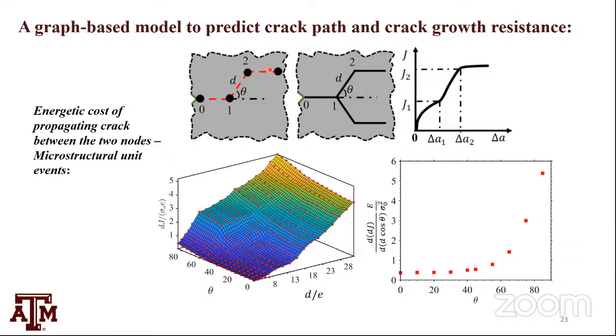I have 4 inclusions. My crack grows from this point 0 to 1, 1 to 2. I can define growth from 1 to 2 as the absolute distance between 1 to 2 and its inclination theta. I can get the increment delta j, j2 minus j1, when crack grows from delta a1 to delta a2, that's this projected distance. I plot this delta j as a function of theta, that's inclination, and d, and it depends on both. And it's not a very simple, nice, clean function. But that's why we just chose this data.